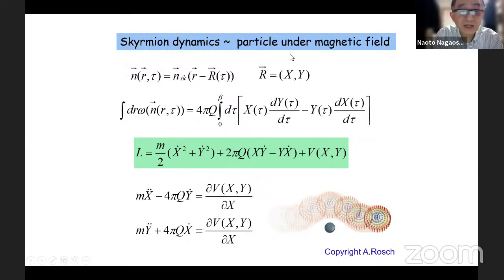Okay, so the skyrmion dynamics, for example, is also controlled by the spin Berry phase. If you plug in the skyrmionic configuration, and the only degree of freedom is a center of mass position, capital R, then this spin Berry phase becomes x y dot minus y x dot. So this means the dynamics of a skyrmion is quite similar to charged particles under a magnetic field. For example, if you have an impurity pinning center here, then the skyrmion is subject to the force, and the velocity is always perpendicular to the force. That leads to avoiding this impurity potential once you drive the skyrmion.